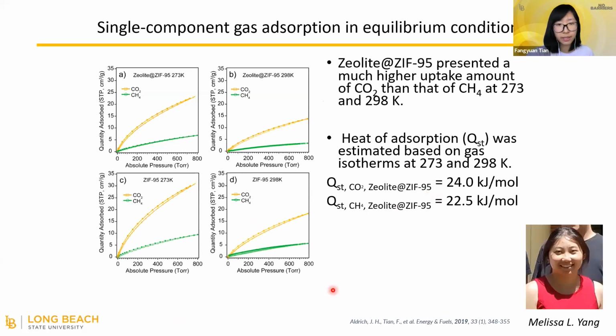My student, Melissa Young, performed lots of these nitrogen absorption analyses. This time we found that this hybrid material, zeolite at ZIF-95, has a pretty good carbon dioxide absorbing amount, even at room temperature, at 298 Kelvin. And we noticed that the QST value, which is the heat of absorption, is relatively low. It's only between 20 to 30 kilojoule per mole. This value indicates that for the zeolite at ZIF-95 hybrid material, this is a physisorption process for carbon dioxide, so it'll be much easier to regenerate. For any chemisorption process, this value could go up to around 100 kilojoule per mole.